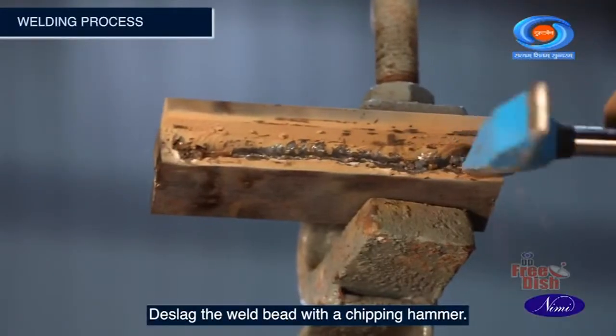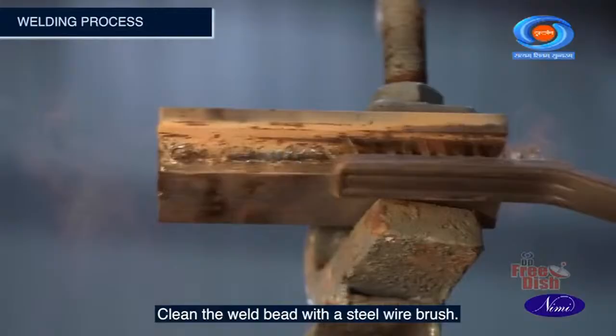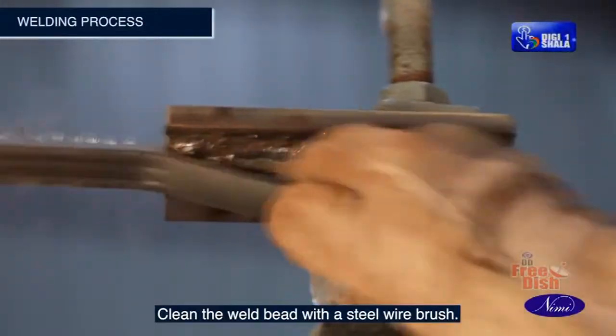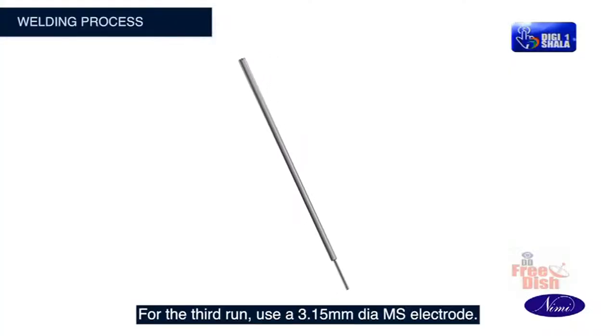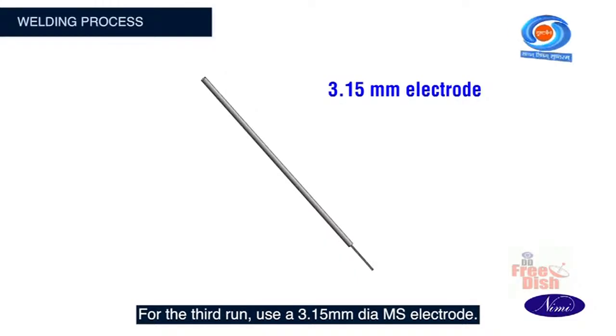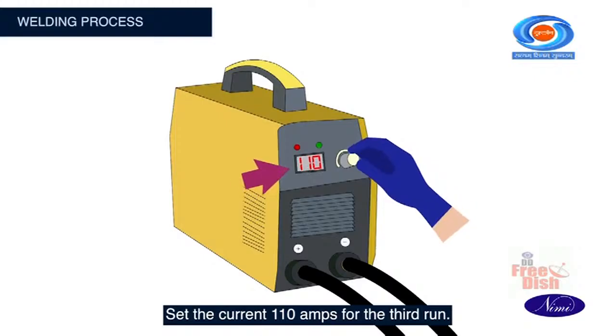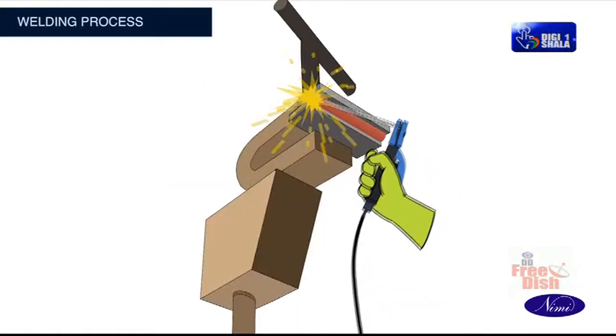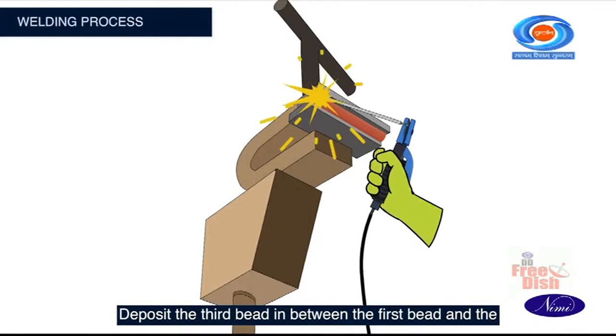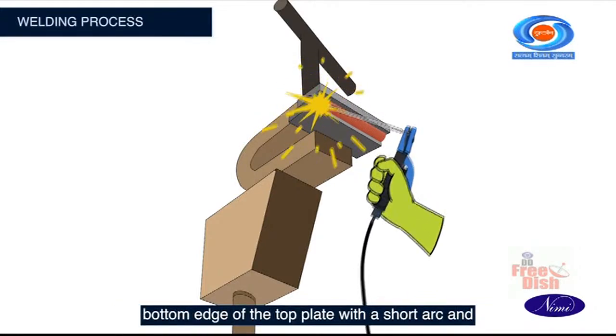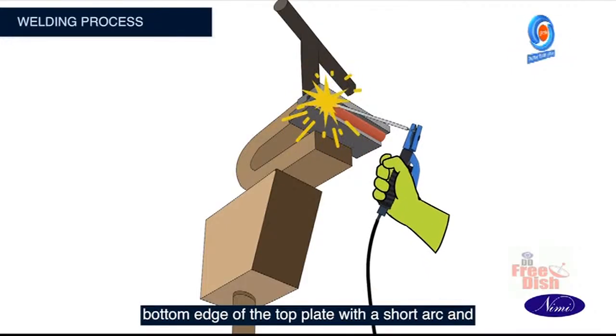Deslag the weld bead with a chipping hammer. Clean the weld bead with a steel wire brush. For the third run, use a 3.15 mm dia MS electrode. Set the current to 110 amps for the third run. Deposit the third bead in between the first bead and the bottom edge of the top plate.